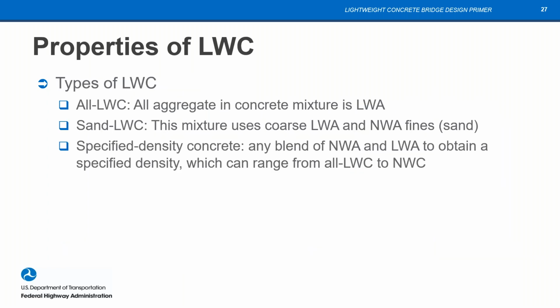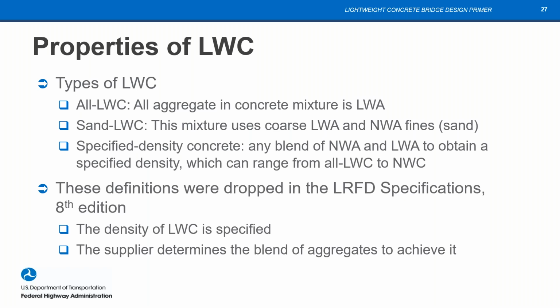There are several types now as we move on into lightweight concrete, having been talking about aggregate up to this point. We'll begin with some definitions of types of lightweight concrete. Here we have all lightweight concrete. As I already mentioned, all of the aggregate is lightweight aggregate. Sand lightweight concrete sounds a little backwards, but what it means is that the coarse is lightweight and the normal weight is used for the fines, the sand. And then there's specified density concrete, which is any blend of normal and lightweight aggregates to obtain whatever density that you want to achieve. The all lightweight and sand lightweight definitions were in the specifications up to the 8th edition, where they were dropped, and we now simply specify the density of lightweight concrete, and the supplier determines the blend of the aggregates to achieve it.